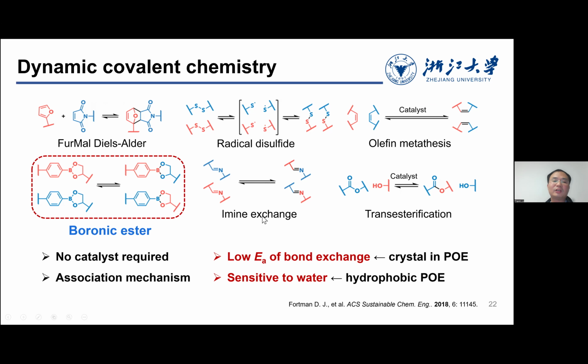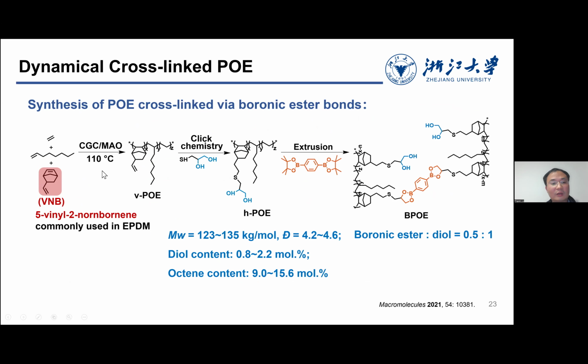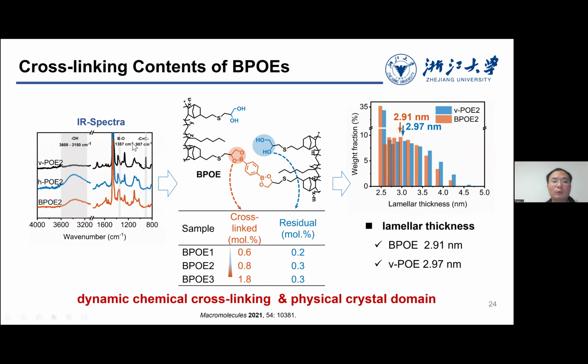So based on this simple idea, we proposed a new chemical route. For example, we introduced some pendant vinyl groups onto the backbone, and we use click chemistry to introduce some diol groups, and these diol groups can be cross-linked by the boronic ester. You can see here this kind of cross-linked structure, and we can tune the molecular weight and their dispersity and also the diol content. By doing this, we form a network. This kind of network we characterize with spectroscopy, and you can see the cross-linked amount and the diol amount.